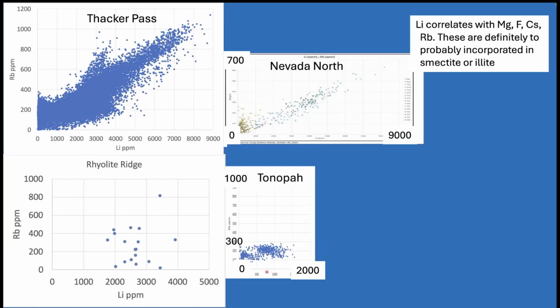We just don't really have enough data for Rhyolite Ridge other than to say that 800 ppm rubidium is pretty high for any average rock. Tonopah does not really show any significant relationship to rubidium and is not terribly enriched. But the incorporation of rubidium in the various clays is consistent with the clay mineralogy and composition. They can incorporate rubidium and notably magnesium, fluorine, and cesium, all of which nicely correlate with lithium and illustrate the different smectite and illite trends.